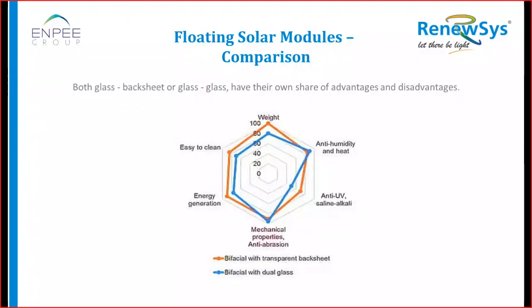So in that sense, as per our understanding and analysis, we found that glass to backsheet at the working conditions of a floating water body is better and sufficient with respect to humidity and temperature. And definitely UV resistance is much better in the backsheet. This is what we understood, that glass to backsheet is the key for floating solar. So glass to glass may have an edge, but it is not really needed. So now I will hand over to Rahul, and he will take forward the next slides.